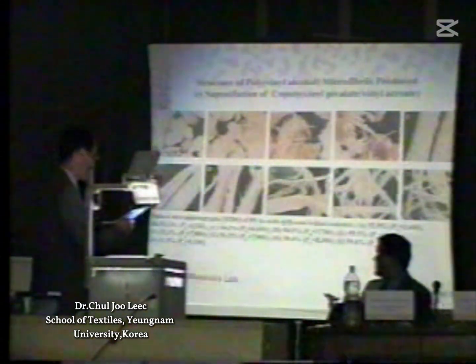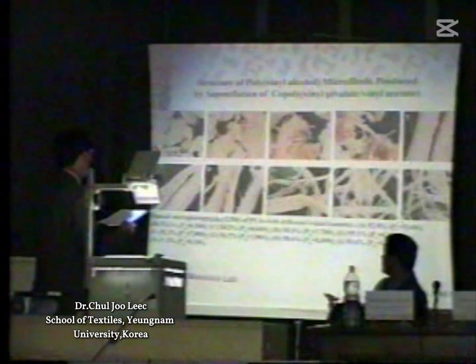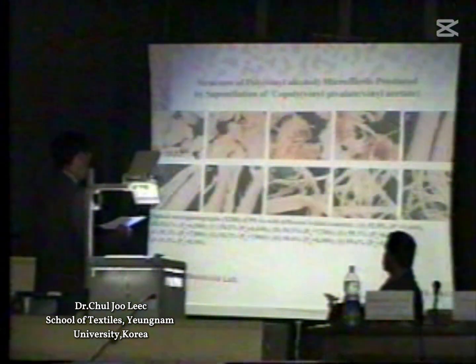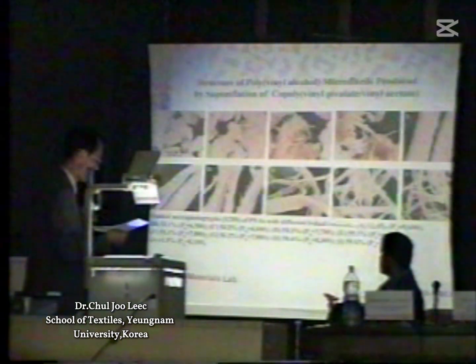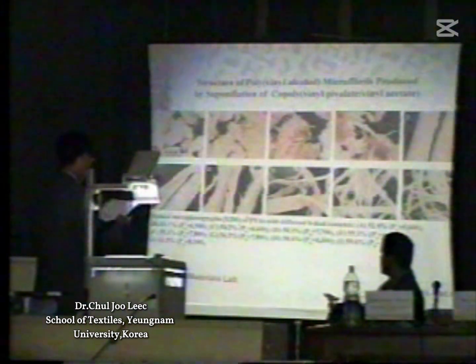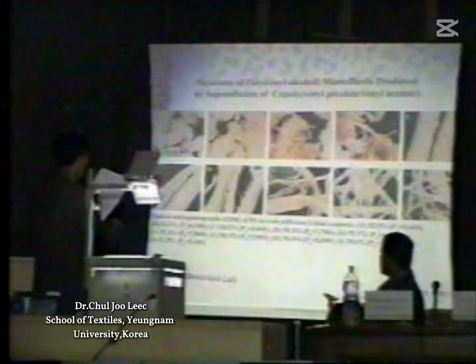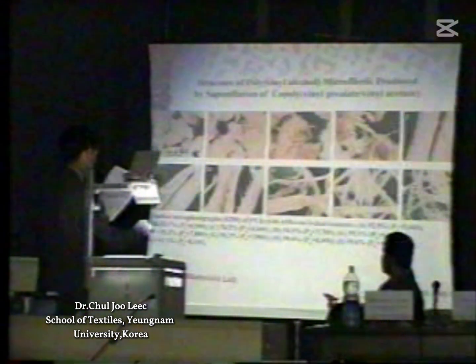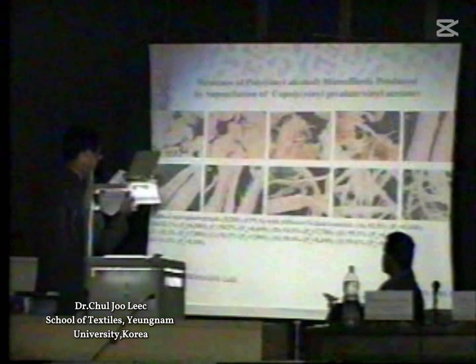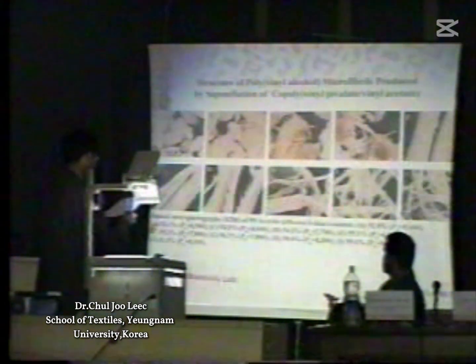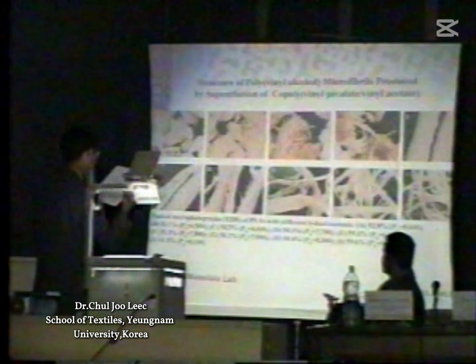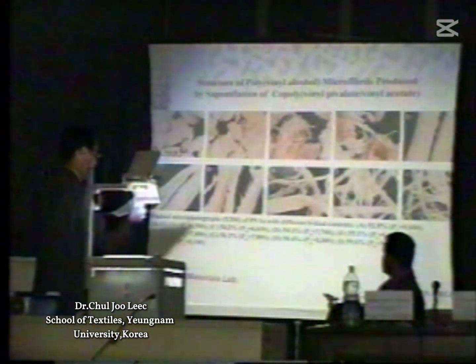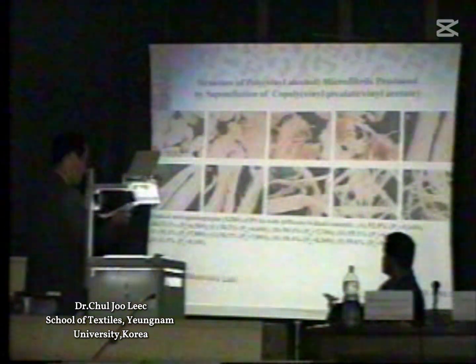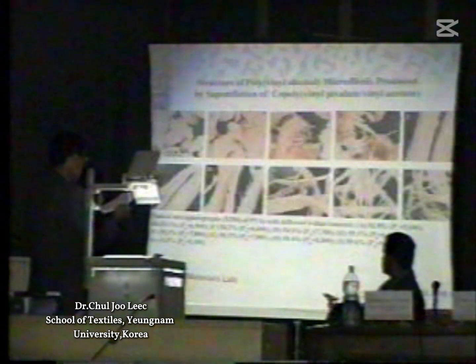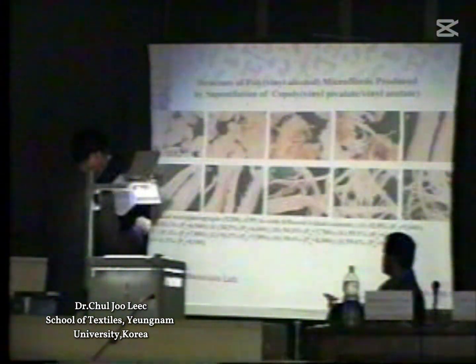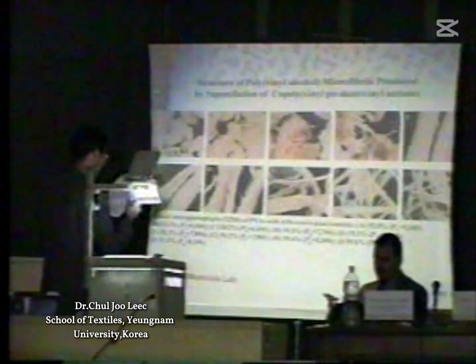This picture shows the shape of polyvinyl alcohol produced by saponification of vinyl pivalate and vinyl acetate, having different syndiotactic diad contents from 52.8% in figure A to 61.5%. As you can see from this picture, PVA with syndiotactic diad of 61.5%, figure J, has very fine microfibrillars. However, PVA with low syndiotactic diad, like figures A and B, is just like a precipitate.